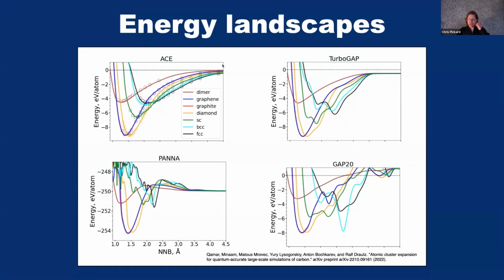So now I want to show you what's a nice feature of these EDDP potentials compared to others that are available in the literature. Here's an example. It was a preprint published by Ralf Drautz, where he's working on these ACE potentials, atomic cluster expansion potentials, and he's justifying why his potential is good. This was just last year. His potential is good because it's smooth for a range of different carbon polymorphs. This is in contrast to well-known potentials such as Tersoff, GAP, and this neural network potential here.